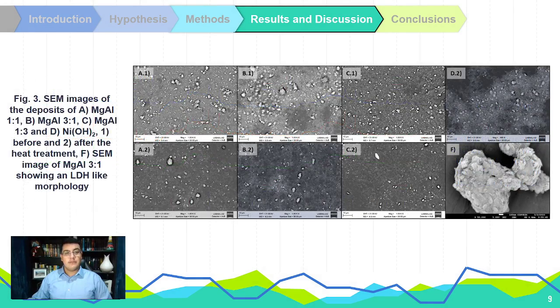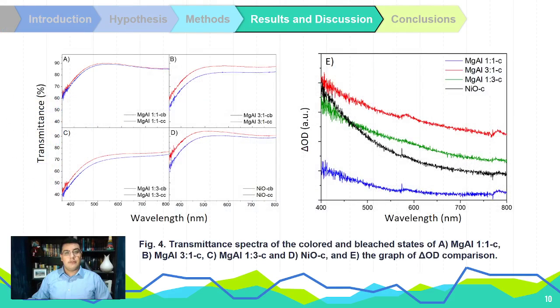On the SEM images of the deposits before the thermal treatment, we can appreciate their homogeneity and abundance. After the heat treatment, we can see that a sintering process has occurred. However, the abundance of the doped deposit is still greater than that of the undoped one. On the last picture, the morphology of one of the materials is shown, it being the typical one of the LDH.